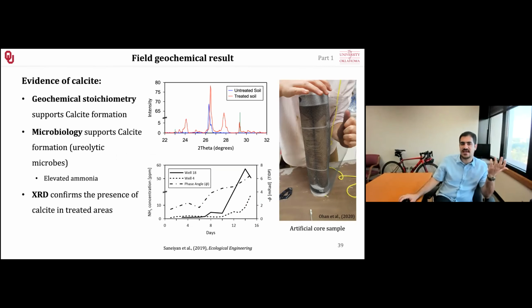It was basically sand. And we were able to see after the treatment, we are seeing evidence of calcite in there. So our microbes were able to produce calcite. Additionally, geochemical analysis on concentration of ammonia showed an increasing trend over time, meaning that the microbes actually decomposed the urea as well.